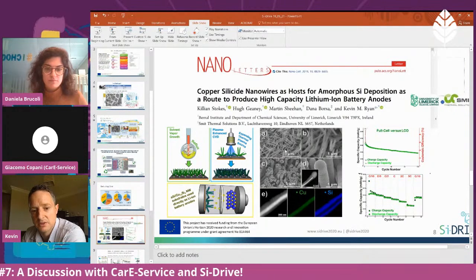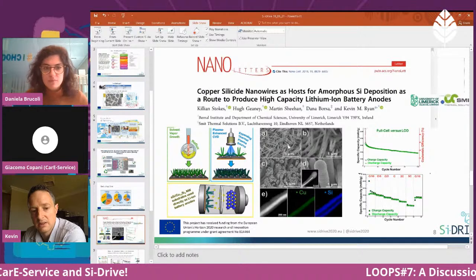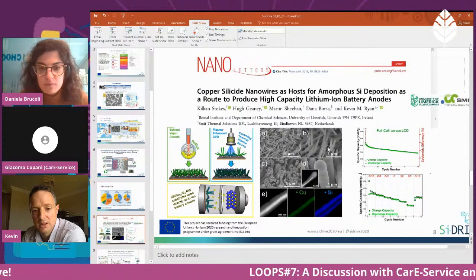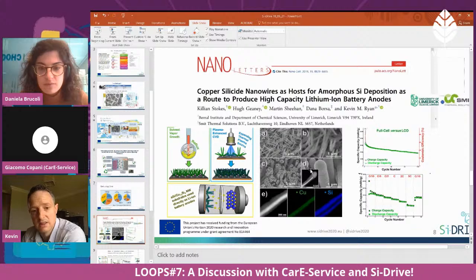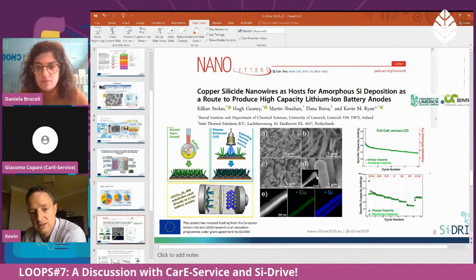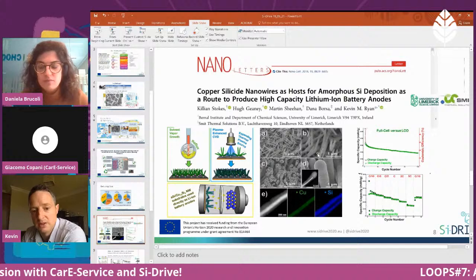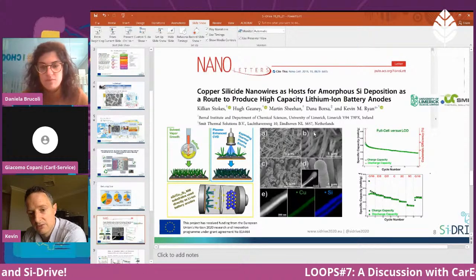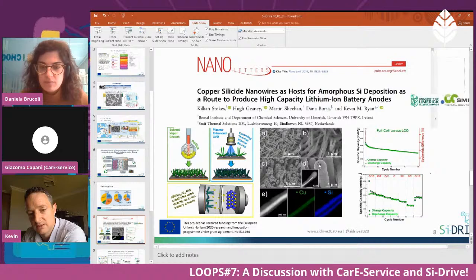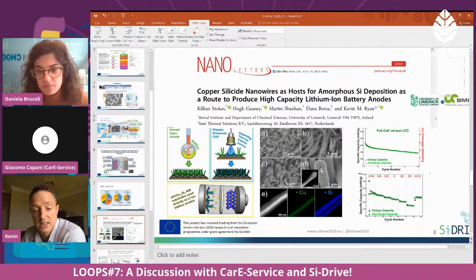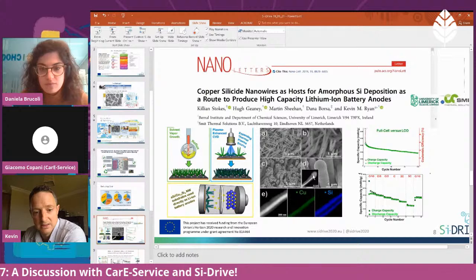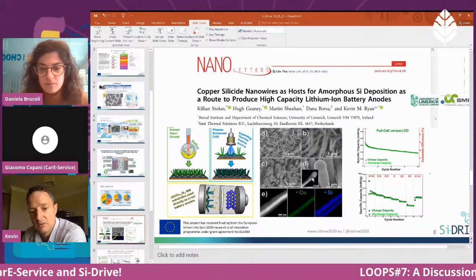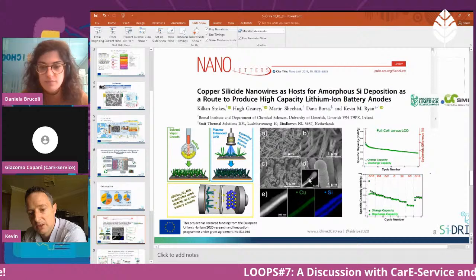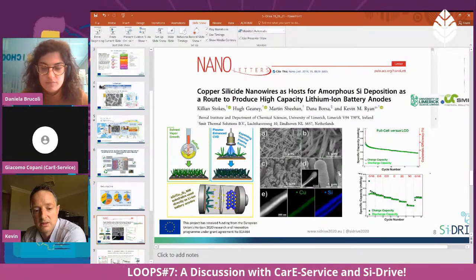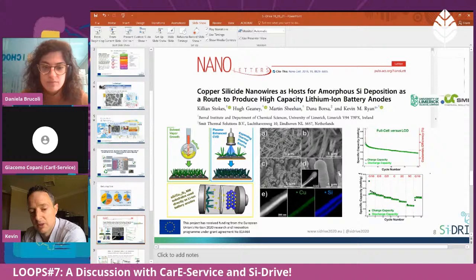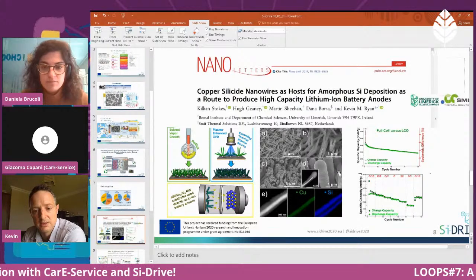And if you look in the middle image here, you can see an SEM image of the nanowires in A. In B, we can see this in higher resolution, and C and D. A and B are before coating, and C and D are after coating. So you can see that we have narrow nanowires, and then after coating, we're getting a substantial thickening of the wires. And if you look at the inset in D, and this is further shown in E, we can see the copper silicide nanowire, which is the brighter white line inside the amorphous silicon nanostructure. So we have a very high loading of amorphous silicon, and we have a very excellent conductive pathway.